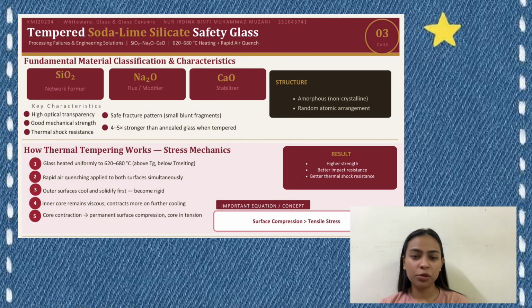But the real strength comes from the thermal tempering process. As shown in the stress mechanics section of this, we heat the glass uniformly to between 620 Celsius and 680 Celsius, which is right above its glass transition temperature but below its melting point. Then, we blast both sides simultaneously with a rapid air quench.